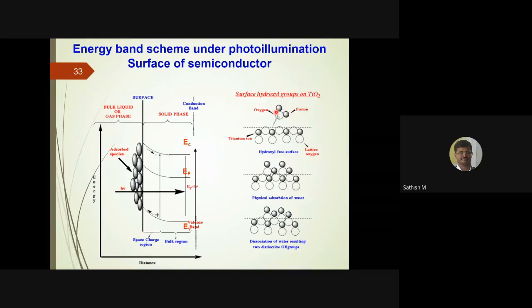If somebody is interested, you can see how this oxidation occurs. Water molecules adsorb on the TiO2 surface, slowly get adsorbed by the surface atoms, and then dissociate, and you can produce some nascent oxygen or hydroxyl radical, so that it can oxidize the pollutant. There are two ways: direct oxidation of the pollutant, or indirect oxidation. In the case of direct oxidation, the electron is received from the pollutant to the, sorry, the valence band of TiO2. In such a case, this pollutant is directly oxidized.